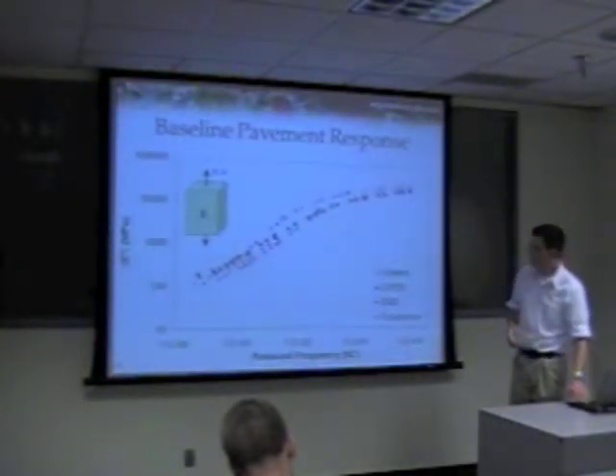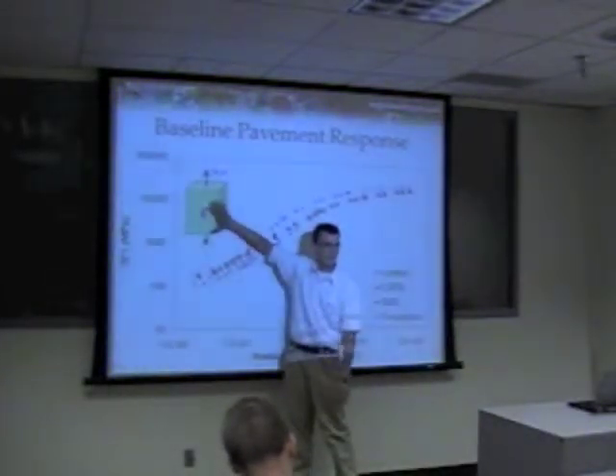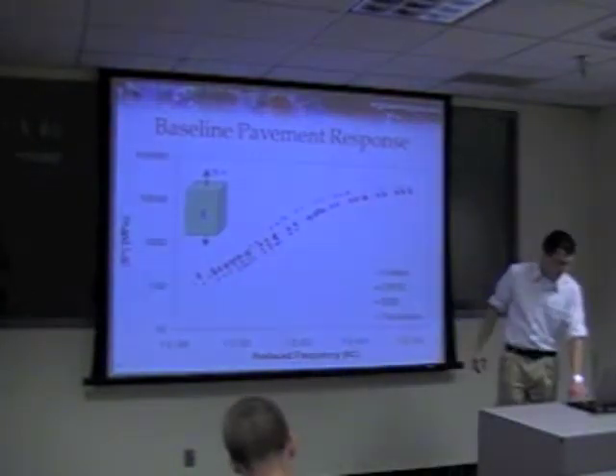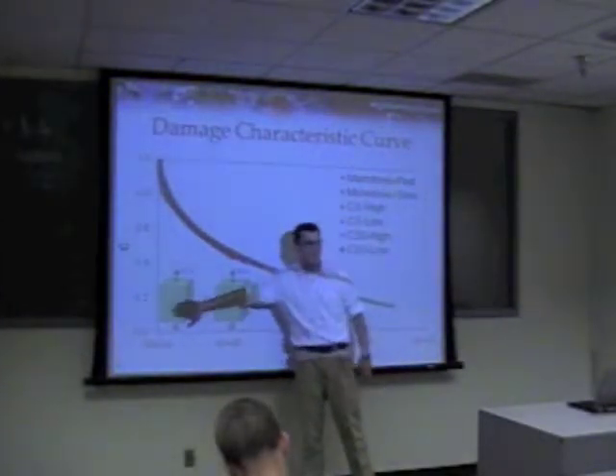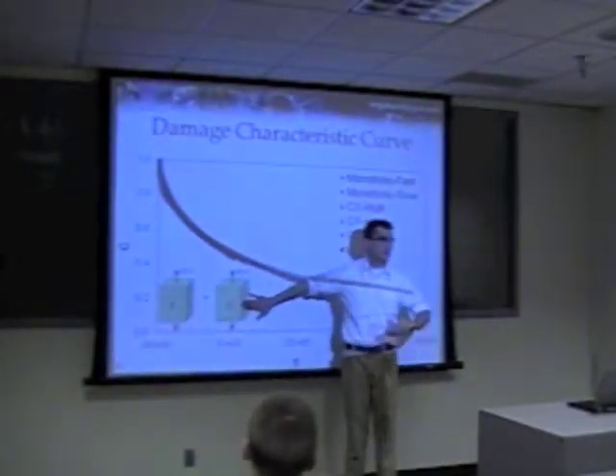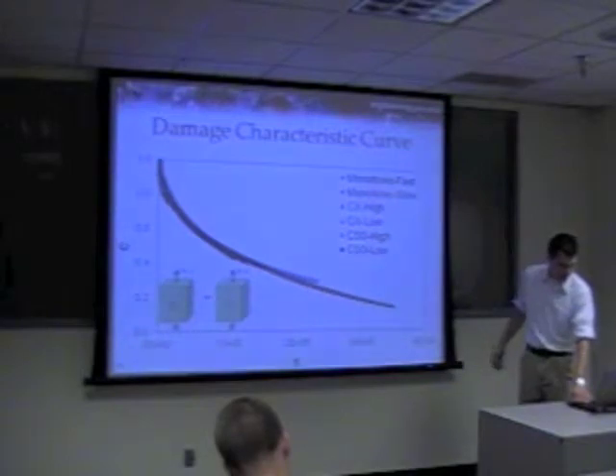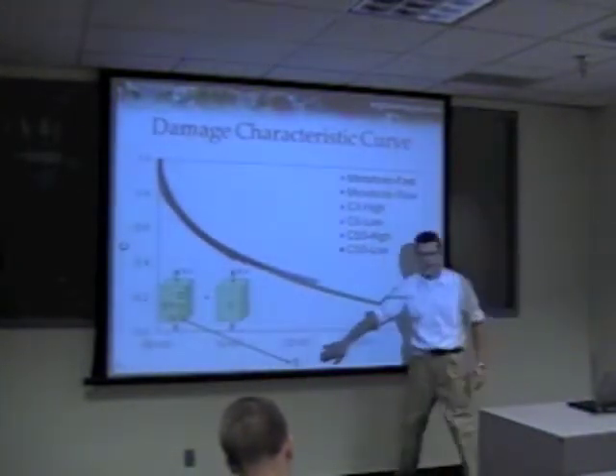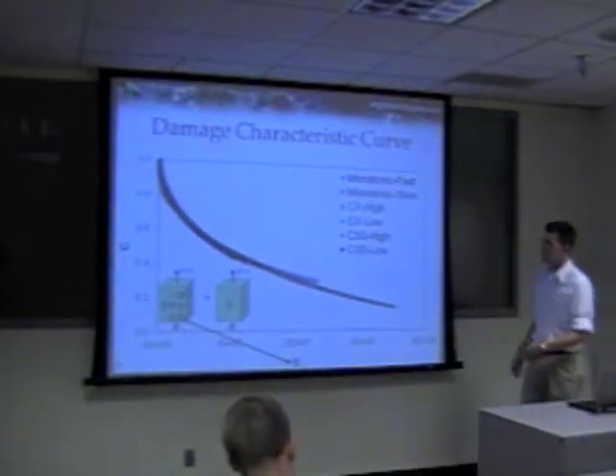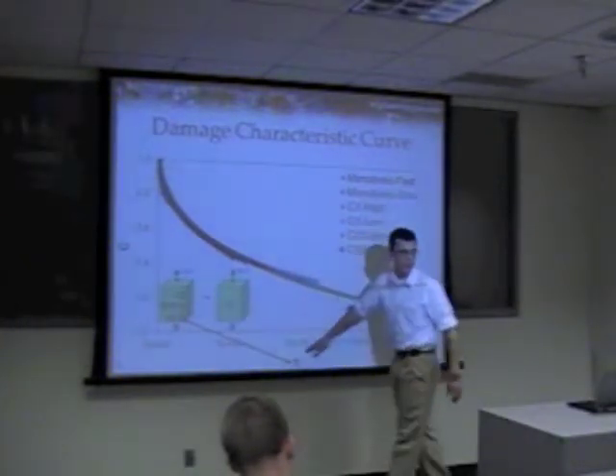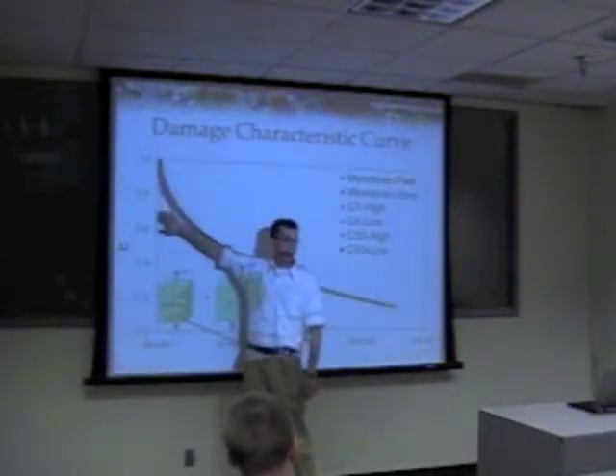The second part of that relationship is about setting the initial state — the no-damage baseline behavior of the material. Then we look at the equation that relates our damaged state to that reduced state. All these little microcracks turn out to be related through the math to a parameter we call S, which you can think of as damage — microcracking versus the effect on the effective or apparent stiffness of the material.